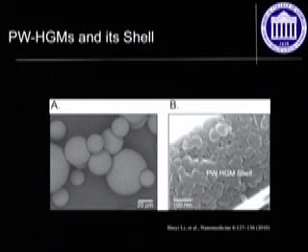This is what it looks like in the scanning electron micrograph. Generally speaking, the bead size is between 10 and 100 microns, with an average size of about 50 microns. This is in the same order as the solid microsphere used for radioembolization. If you increase the magnification, you can see on the shell surface there are interconnected worm-like channels.